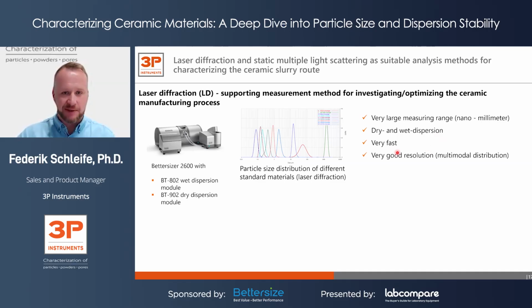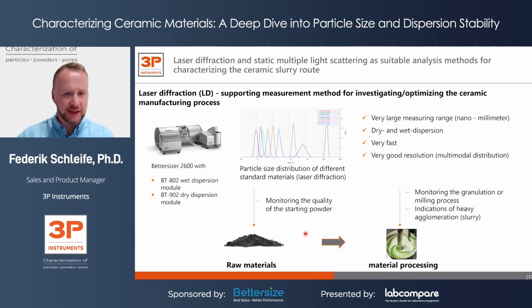A laser diffraction measurement is pretty fast. You get a result within a few seconds, and it gives you very good resolution. So even if you mix different powders with each other, you could easily resolve a multimodal distribution. So therefore, you can easily monitor the quality of the starting powders, your raw material, and you can also monitor any granulation or milling processes, or later on identify and indicate heavy agglomerations if you check for the final slurry.